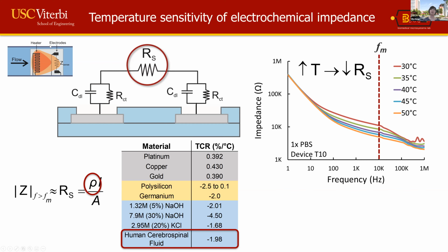What we do is we heat the fluid up, and the heat is carried by the flow towards a pair of open sensing electrodes. And if we look at these sensing electrodes at high enough frequency, we essentially bypass the double layer capacitance. And so effectively, we're looking at just changes in the solution resistance.